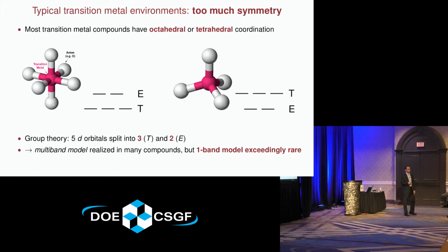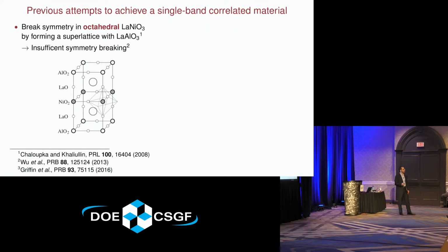There have been decades-long searches for new superconductors, especially ones similar to the cuprates. Unfortunately, they haven't been successful. I'll mention a few recent strategies or ideas to try to achieve this one-band model. So the first was to take an octahedral compound, namely lanthanum nickelate, and to form a kind of complex structure in which one makes a superlattice, so one layer of lanthanum nickelate and one layer of lanthanum aluminate, and then to go sort of every other. And the idea here was simply to explicitly break the symmetry of those two e orbitals. So you get one that goes up in energy, one that goes down, and hopefully you get this kind of one-band correlated material. Unfortunately, the experiments have shown that really one just doesn't get enough symmetry breaking. So it seems like starting from a high symmetry coordination like octahedral is difficult to achieve a one-band model.